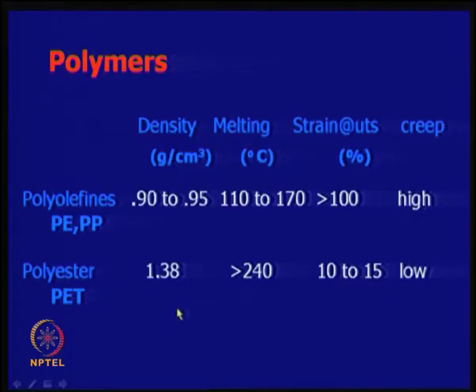The strain at ultimate tensile strength could be a little higher, and creep could also be higher. Some polyester materials have a higher specific gravity, or density, and a higher melting point, and you can get the tensile strength at 10 to 15% strain. For example, if you take a stiffer material, it will reach the ultimate tensile strength very quickly, and the creep could also be low. In some applications we do not want a lot of creep, so it is very important that we choose the materials properly. One should ask what type of polymer you have in a particular geotextile.